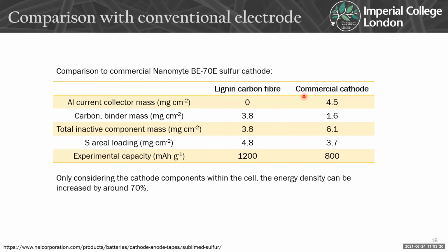So just as a quick comparison then, I just wanted to show there's a commercial sulfur cathode available that is 70 weight% sulfur loading, but this is a slurry coating on aluminium foil. So I just wanted to compare that actually here we can lose some mass by not having to have the aluminium current collector. Although our areal carbon loading is higher than the amount of carbon black and the binder that they put in, overall our total inactive component mass is lower, and we've managed to achieve a higher sulfur loading. And then in terms of the experimental capacity, the NEI website states that their cathode can achieve 800 milliamp hours per gram, but in this case, we've achieved around 1200. And so if we only consider the cathode components within the cell, then actually we can increase the energy density by around 70%, which is not bad at all for some initial results.